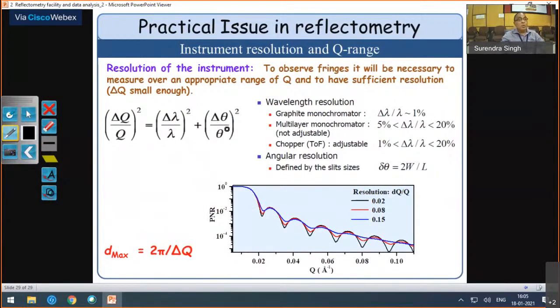In our case, mostly for reflectivity, if you have a monochromator base like graphite, this delta lambda by lambda becomes 1%. But in our case, silicon, this is very small, around 0.1 degree, 1% or so, because we don't have a higher mosaic spread silicon crystal. Depending on the monochromator you can change this value, but basically this resolution for a PNR instrument is mostly decided by the beam dimensions.